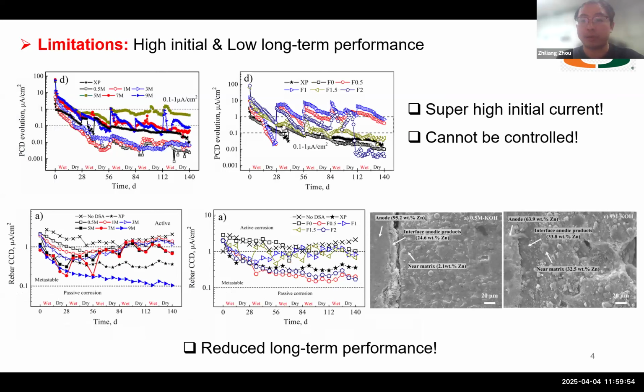However, these two proposed methods are not perfect. It was found that with the increased pH value and the increased porosity, the protection levels of sacrificial anodes are extremely high at the initial time, but their long-term protection levels are reduced and not sufficient. Our experimental data confirmed the initially high current flow and the reduced long-term performance. So we need to do something. We need to further modify the sacrificial anodes.